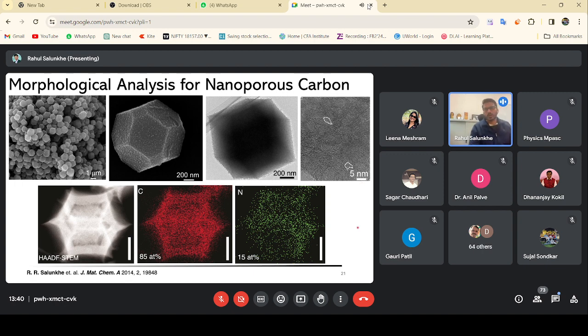So even the particle size of these particles can vary from 300 nanometers to 5 micrometers. By changing the reaction conditions, we can change the size of these particles. The HRTEM shows the formation of the micropores. Further HRTEM I will show the actual pore structure also. This is a STEM HAADF image, and from the TEM elemental mapping we can see that 85 atomic percent is carbon and 15 atomic percent is nitrogen. This is what a typical MOF-derived carbon material looks like.